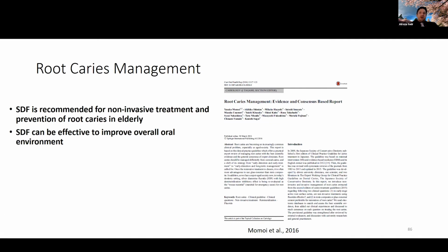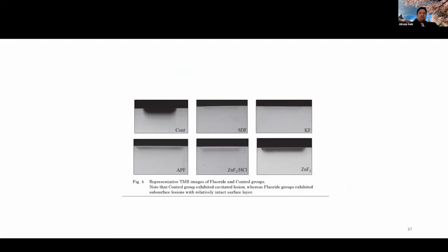But in 2016, I believe, yes, they came out with the root caries management kind of clinical protocol. And in this Japanese article, which is from the Japanese Journal of Conservative Dentistry, and also published in English, they say that SDF is still recommended for non-invasive treatment and prevention of root caries in the elderly, and can be effective to improve overall oral environment. And by that, it's because of the antibacterial effect of the silver ammonia in the SDF that will improve overall oral environment for root caries cases, for elderly, for those who are sort of difficult to control with conventional dentistry.